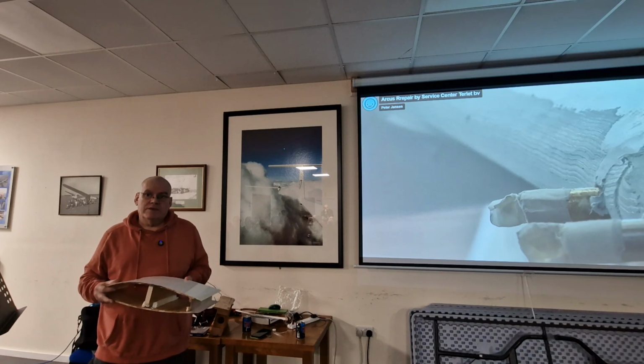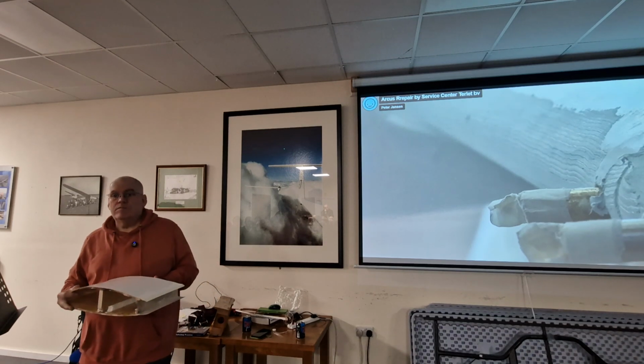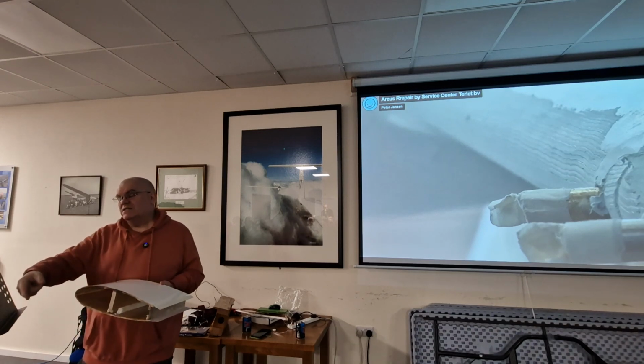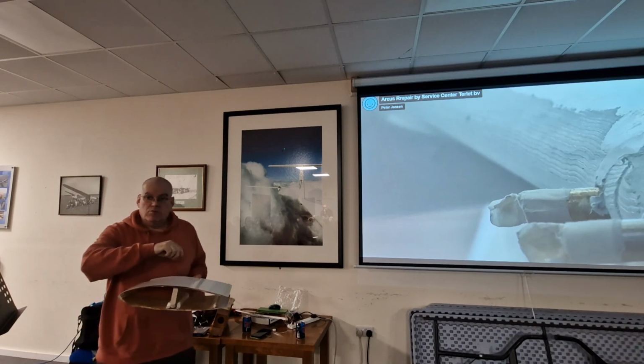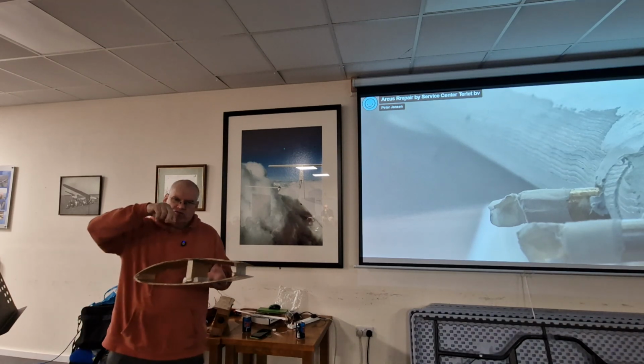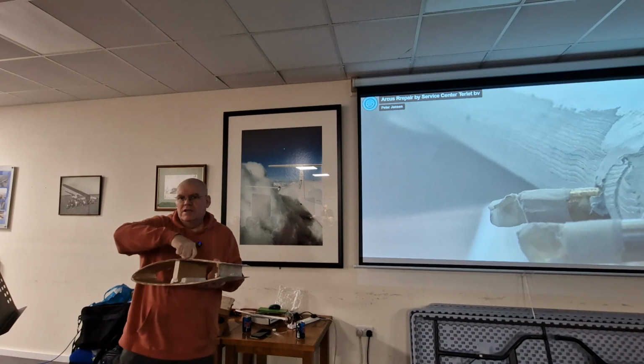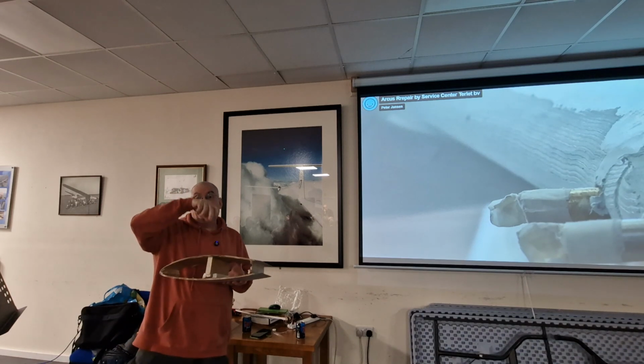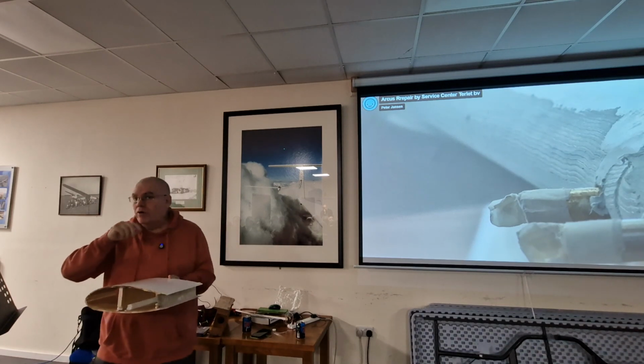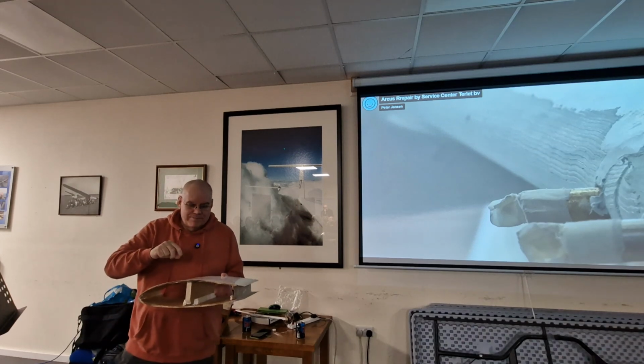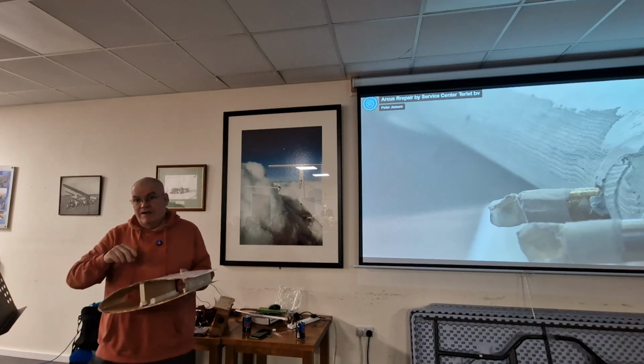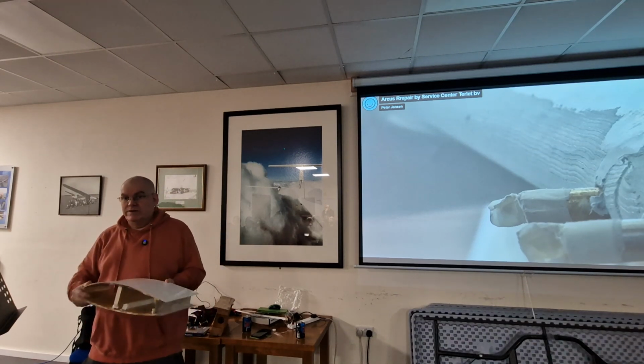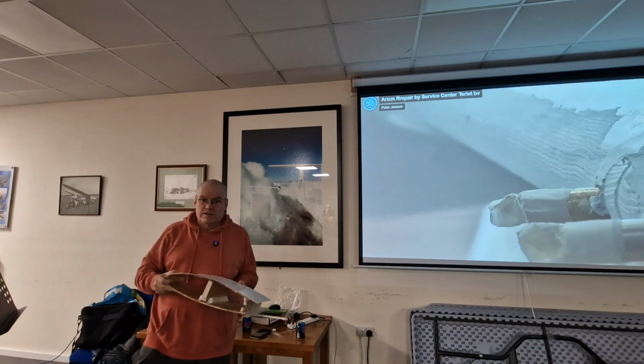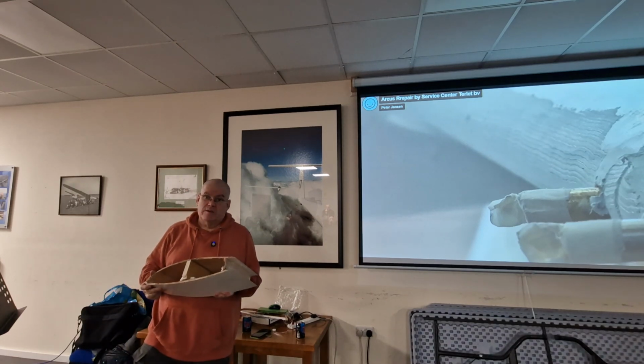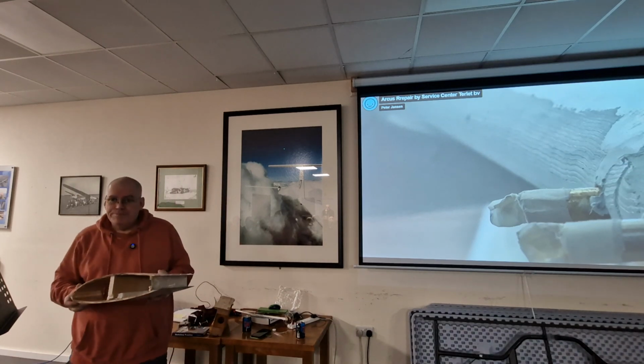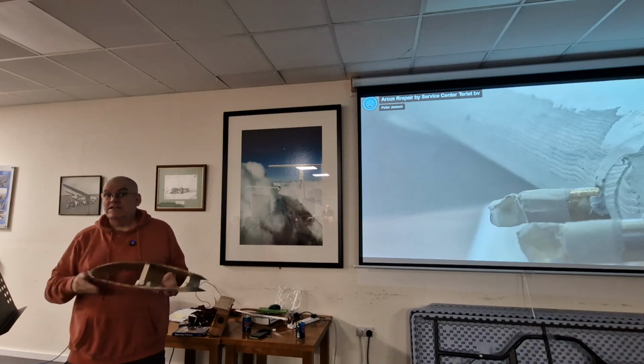But there can be, whenever you're taking the resins beyond their original temperature, because by the time you're trying to get into the middle of the dent, you expand it to about 80 degrees and push it out. It's not an exact science. It can go wrong. But generally, we've done some very, very 10-foot long dents, which the insurance company thought were going to cost 15 grand to fix. We actually did it in an afternoon. But it's high risk.